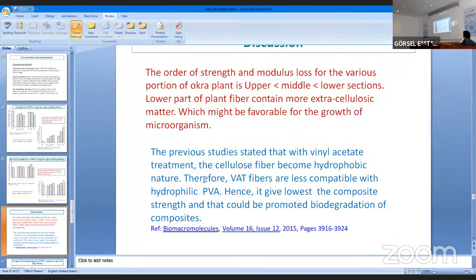The discussion is mainly the order of strength and modulus loss for the various portions of Okra fiber. Upper is less than middle, and lower is maximum. The lower part of the plant fiber contains more extra-cellulosic matter, which might be favorable for growth of microorganisms. On the other hand, previous studies stated that with vinyl acetate treatment, the cellulose fiber becomes hydrophobic in nature. Therefore, vinyl acetate treated fibers are less compatible with hydrophilic polyvinyl alcohol. Hence, it gives the lowest composite strength, and that could be promoted by degradation of the composite.